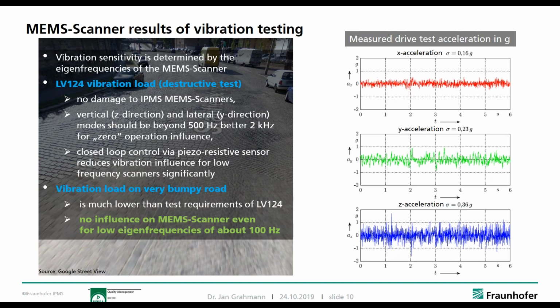The next point is that I showed you that the Z direction, the vertical direction, and the lateral Y direction are the most critical ones concerning an operation influence. And there we've seen, based on the destructive test, that below 500 Hertz, you have to look a little more closely concerning operation influence. Beyond 500 Hertz, you basically have no problem, and at 2 kilohertz, you don't even have to look at operation influence on the scanners.